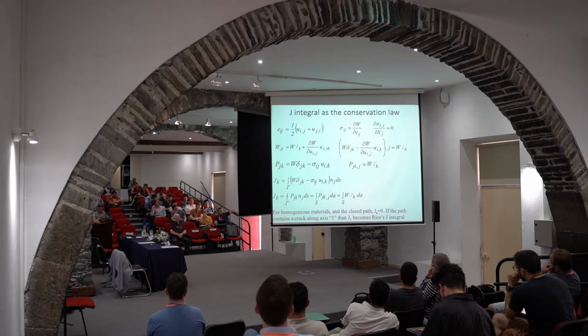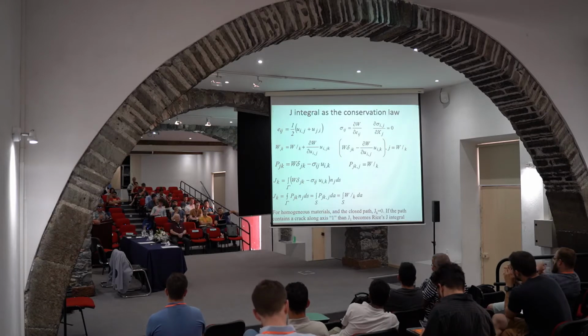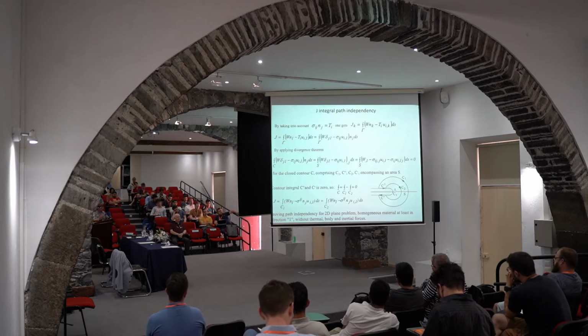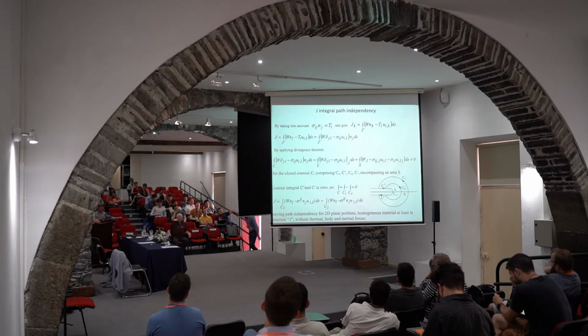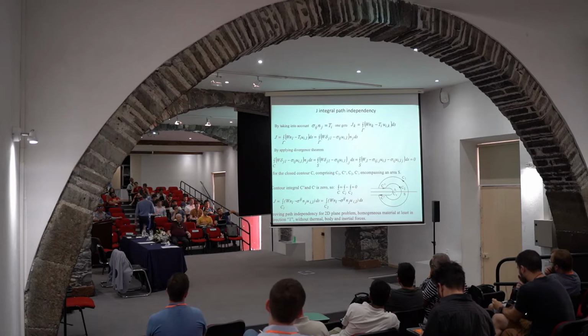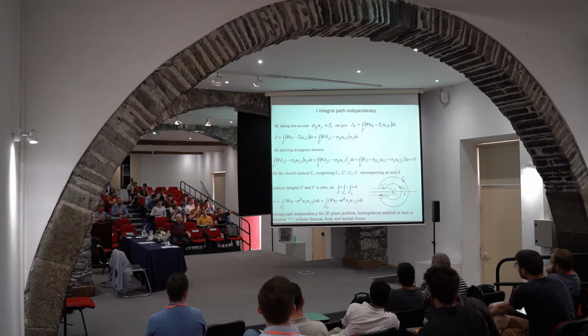a closed path integral and also transformed to the area integral, which becomes Rice's J integral if we put k to be 1, if we consider just a crack along axis 1, which is abscissa, which is the x-axis. After we do that, we can also prove that it is a path independent integral. Once again, there are a couple of equations written in a simple form, but not as simple as they look, so we are not going into details. I just want you to see what is behind the story of the J integral as a conservation law.